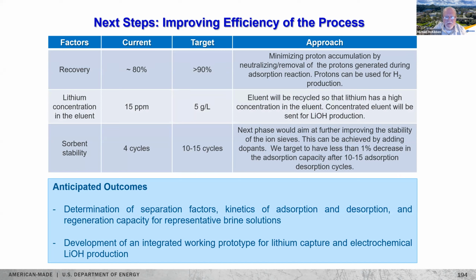And we want to test the absorbent stability for more than 4 adsorption-desorption cycles, possibly by using iron dopants. We expect to demonstrate improved separation from competing ions, faster kinetics of adsorption, desorption, and more accurate regeneration capacity by using actual Salton Sea brines at relevant power plant temperatures. This will allow us to develop an integrated working prototype that can be tested in a real plant setting. Next slide, please.